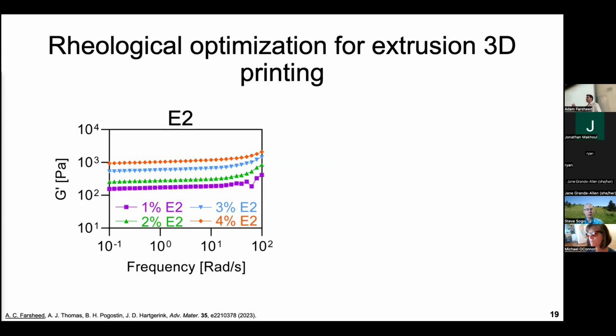And so if we just add to the concentration of our material, what we see on this graph here, which is called a frequency sweep, is as we add material, the G prime on the y-axis is going to increase pretty modestly. And I just want to call to your attention that the axes in these graphs are on a log scale. So a small difference is probably much bigger than you might think.